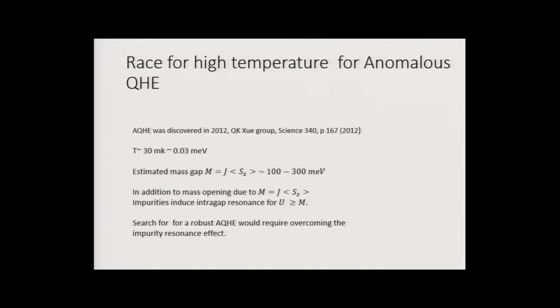Yes, that's true. So my point is that what I'm saying is important to understand how we can go from 30 millikelvin to the raw energy scale, which is the 300 millielectronvolts, okay? Because in your case, for graphene, for instance, if you do the back-of-the-envelope estimate of Landau level splitting and the temperatures required to get the quantum Hall effect, you can get there if you have clean enough samples. Here we have this 3-4 orders of magnitude discrepancy.